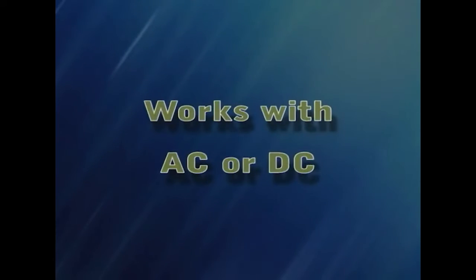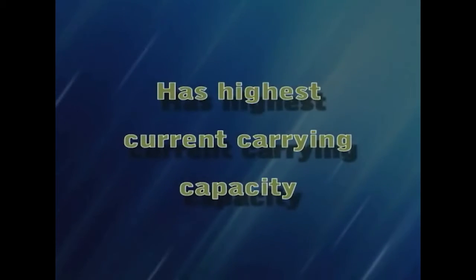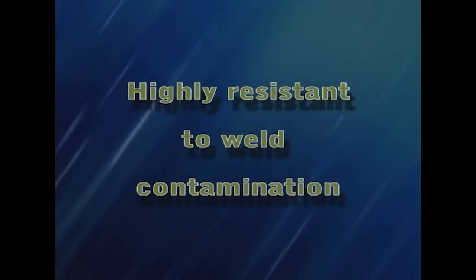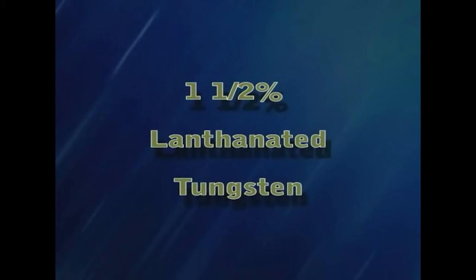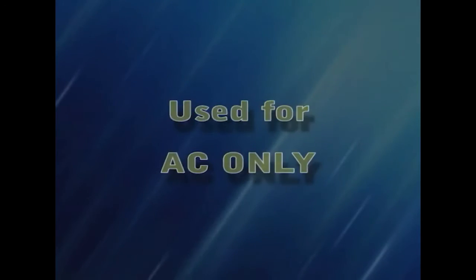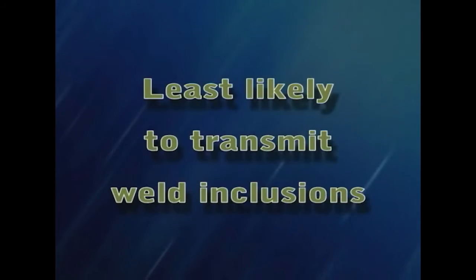Lanthanated tungsten can also be used for either AC or DC welding. Lanthanum increases the current carrying capacity of tungsten by 50%, and it is highly resistant to weld contamination. 1.5% lanthanated tungsten, the most popular percentage, is color-coded gold. This is another good choice for general-purpose welding. Zirconiated tungsten is used for AC applications only, and especially for sensitive work where the slightest inclusion of the electrode in the weld bead would cause problems. It produces an extremely stable arc. Zirconiated electrodes are color-coded brown.